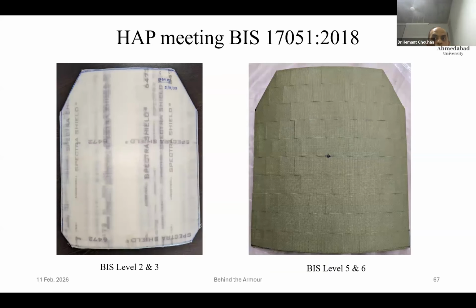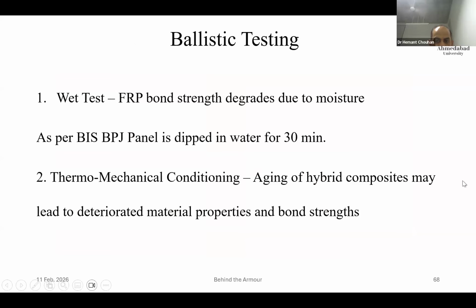By this we developed BIS level 2 and 3. This is how the panel looks, meant for 8 rounds of AK-47 or the BIS level 3 mild steel ball. And this one is the type of panel which is made for BIS level 5 and 6, that is AK-47 and sniper with hard steel core projectile. Is this sufficient? No. These panels are to be tested against thermomechanical conditioning and wetting parameters.